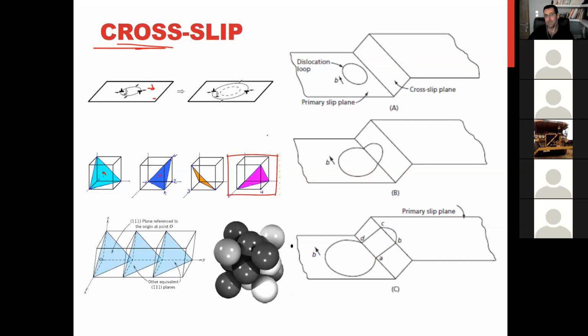But something happened. When this happened, when this dislocation comes to another plane, which has angle with original plane, yeah, not necessarily all these Burgers vectors remain. Just Burgers vectors of screw dislocations remain in the plane of a slip plane. Okay, it means this portion and this portion, yeah.